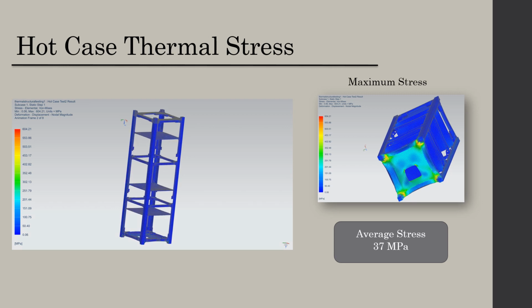However, as seen in the maximum stress figure to the right, the negative Z plate on the CubeSat has a significant amount of stress imposed to the surface. This was caused by an improper thermocoupling to the plate, which caused a large decrease in temperature. Because of this, these stress values are not accurate to the true response of the model and can be ignored.